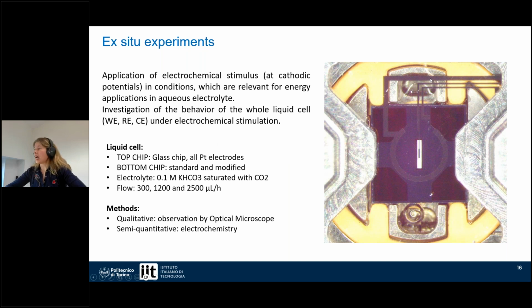So this is how it looks when we close the cell for the in-situ experiment. So basically, you see the small chip and the big glass chip. The glass chip has all platinum electrodes in this case, and we will investigate what happened in the cell when we close it with the standard or with the modified small chip. You can see from this image here that the counter electrode and the reference electrode are actually aligned with the bypass channel. So where they are present, we actually have quite a lot of electrolyte.